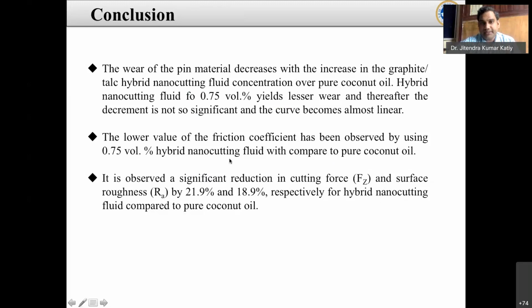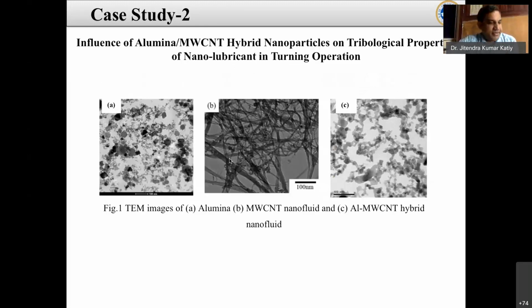the pure coconut oil. So another case study: we also used alumina and MWCNT hybrid nanoparticles for the tribological properties in a turning operation. That turning operation we performed on an aluminum alloy. So these are the TEM images of this cutting fluid. You can see the alumina, how it looks, and the multi-wall carbon nanotubes are also uniformly distributed in this hybrid nano cutting fluid. These are observed by transmission electron microscopy.